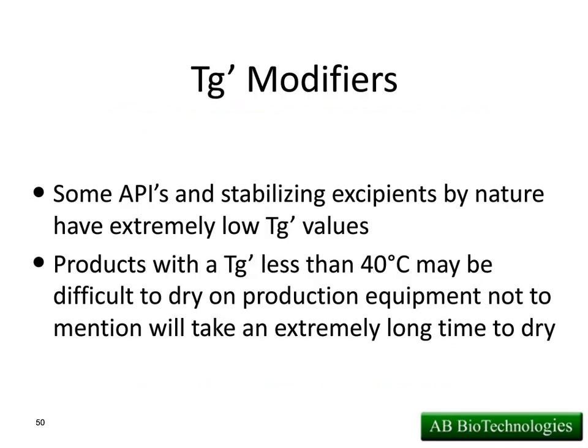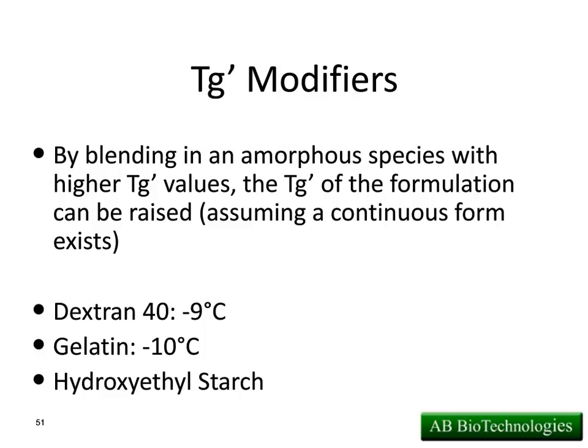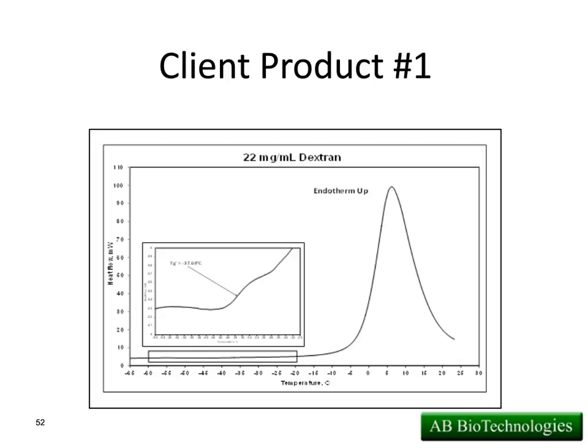Now, one of the tools that we have in our toolkit is what we call glass transition temperature modifiers. So we can actually blend in amorphous phases with higher glass transition temperatures and raise the overall glass transition temperature of our formulation to the point where we can actually freeze-dry it in a decent amount of time. What we generally reach for most is dextran 40, or sometimes we'll even use gelatin. These are both very well suited to raise glass transition temperatures to get them into a manageable temperature that we can actually freeze-dry them. So for this first run under the DSC, we blended in 22 mg per mil of the dextran, and we went from a glass transition where we couldn't even see it up to about negative 38.